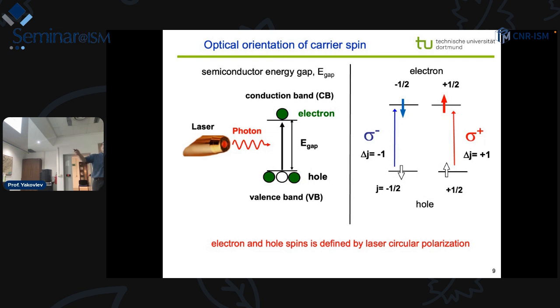And if this spin orientation is not lost by some other mechanisms, when we can wait until recombination, this electron will recombine with this hole and it will emit sigma minus polarized light. And we can measure the degree of the polarization and see how much spin relaxation happens, or not, or change temperatures, magnetic fields, and play with that. Of course, if we come with sigma plus polarized light, we will make opposite orientations of the carriers.